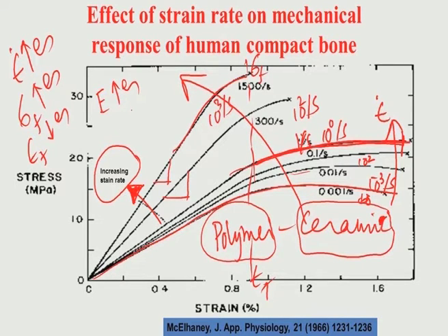So, from this stress strain response, it must be clear to you why, during high strain rate impact or during an accident, a person can undergo bone fracture very easily. In an accident, when the bone experiences very large impact, it shows a little bit higher strength, but the fracture strain is fairly low. Therefore, natural bone is more prone to fracture because of limited plasticity.